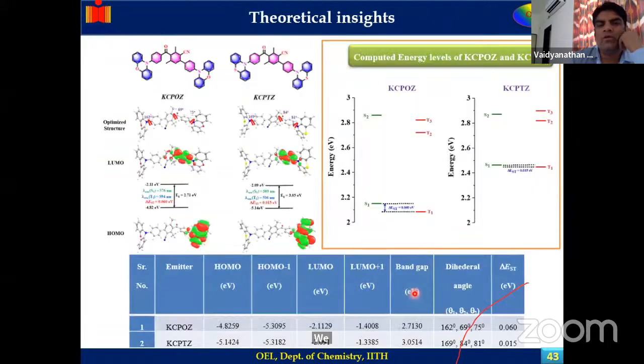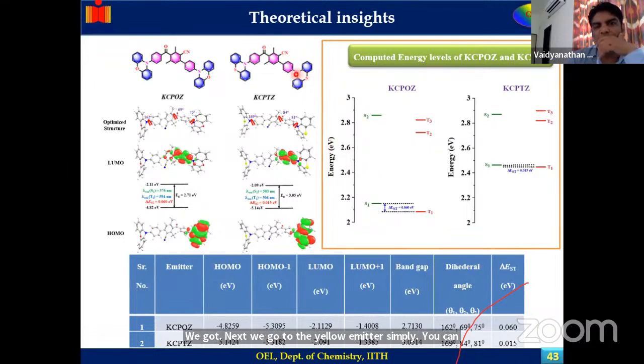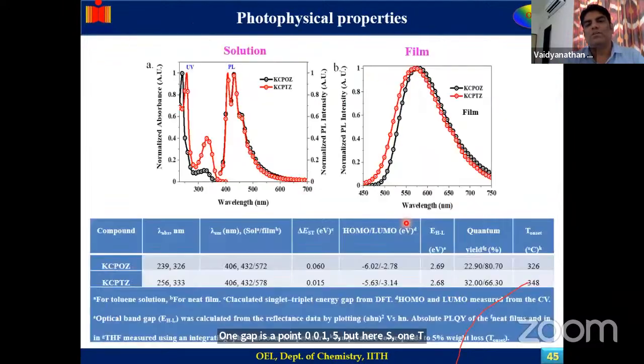Next, we go to the yellow emitter. Simply you change carbazole to phenoxazine and phenothiazine, NS and NO groups. What we found is both of them give green and yellow color, which is very interesting. The S1-T1 gap here is 0.015, but here the S1-T1 gap is 0.06, which are also very interesting values.